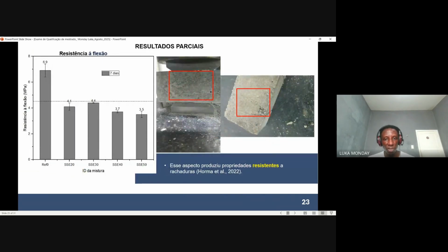On the aspect of flexural strength, as the substitution increases, the flexural strength tends to decrease. But this material demonstrates a crack-resistant property, which shows that in a load-bearing application or an external wall, it tends to resist the effect of forces in either the horizontal or vertical direction, based on the resistive property it displays here.